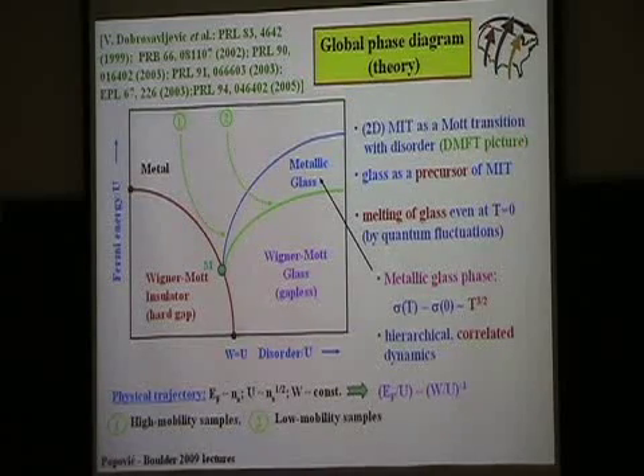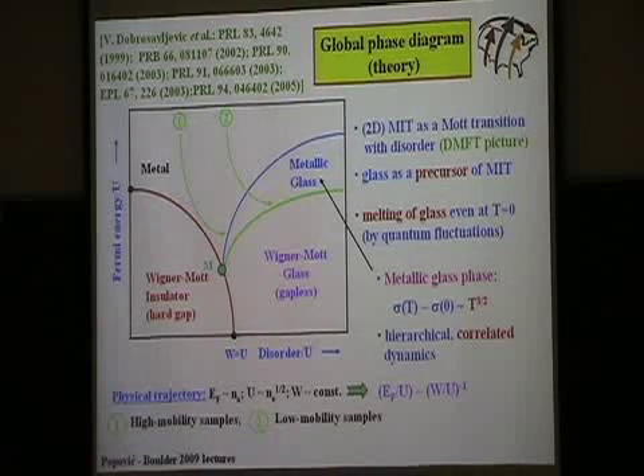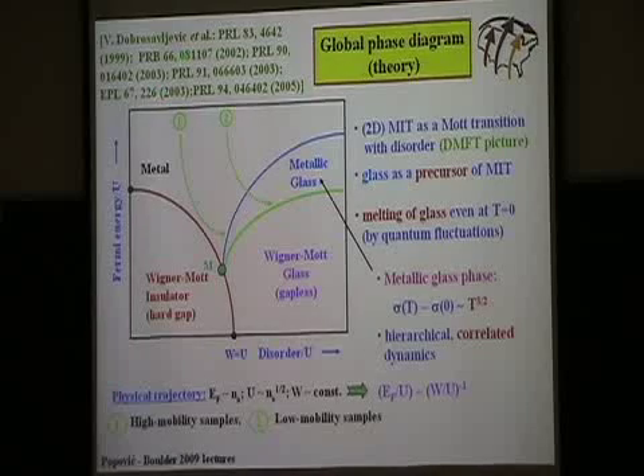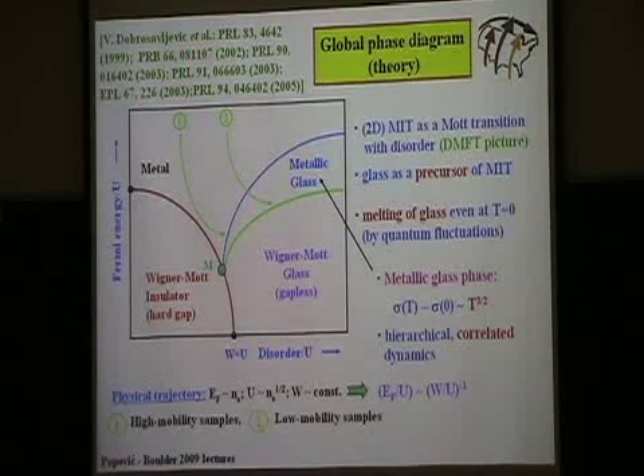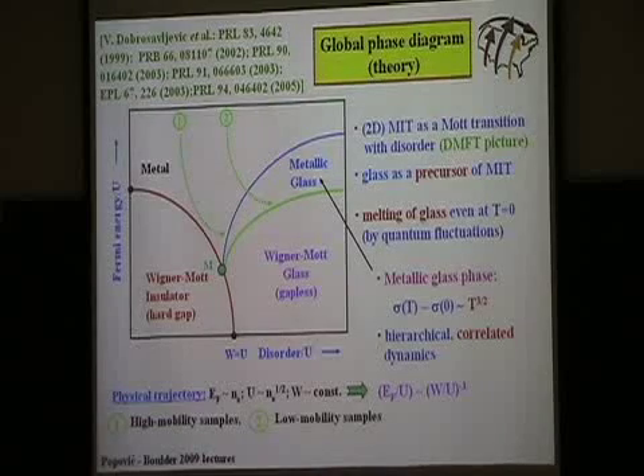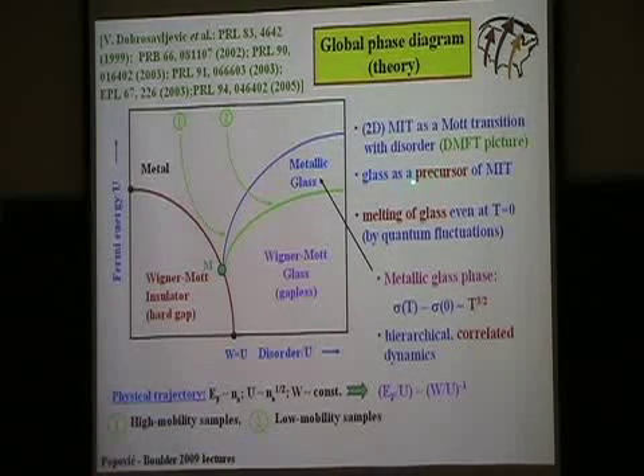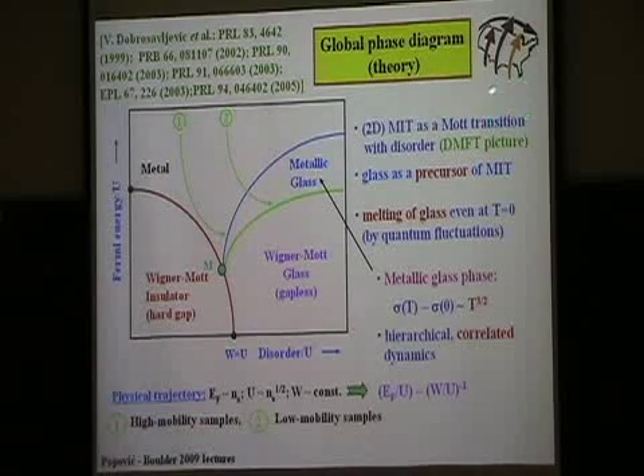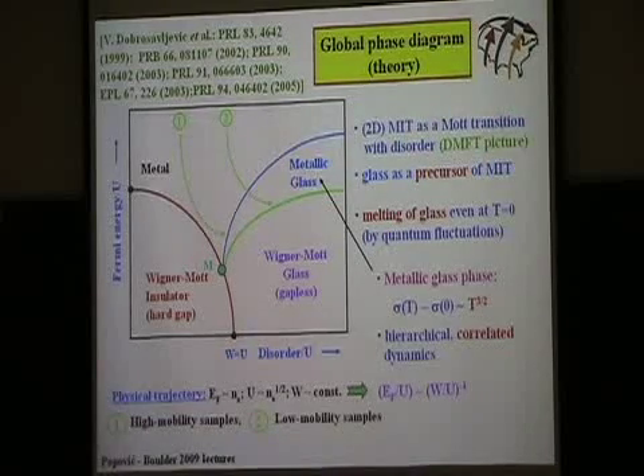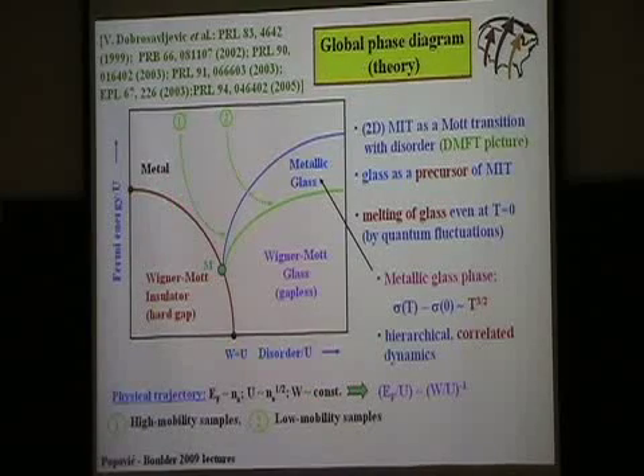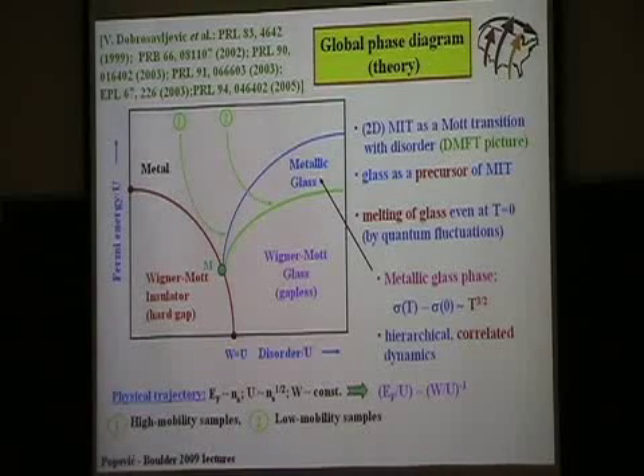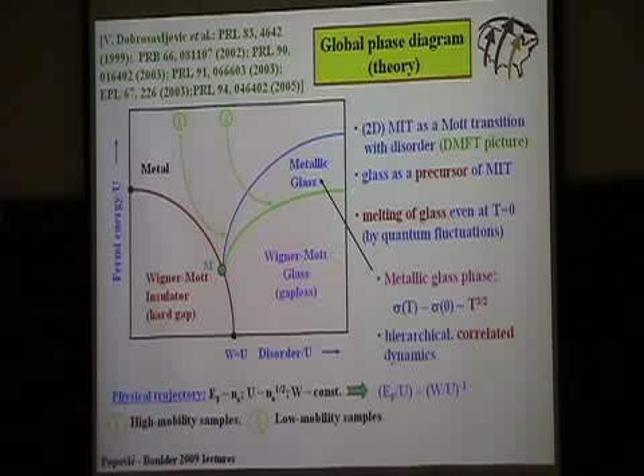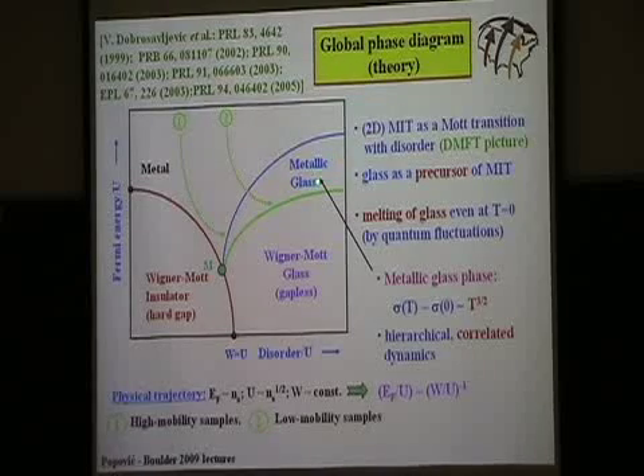theoretical phase diagram, which has some relevance, I think, to what we have been doing, and this is work that has been going on for a number of years in the group of Dobrosavljevic, also at FSU. So this is the phase diagram for the metal-insulator transition, the MIT, where all interactions are important along with the disorder. And theorists always have a different way of plotting things, which is different from what we do in the experiment. Basically, for sufficiently large disorder, they find the emergence of this intermediate phase, which is metallic and glassy.